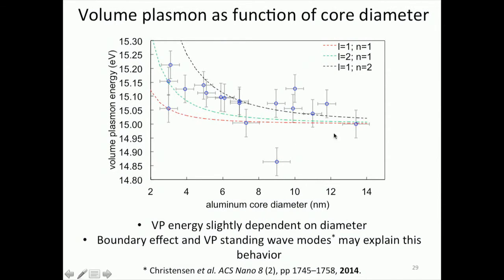Here I simulated the 3 lowest order modes of the volume plasmons, and we see a relatively good agreement between them. One thing that this suggests is that in these aluminum nanoparticles and nanocylinders, we may have excitation of only low order volume plasmon modes. So this is an interesting result.